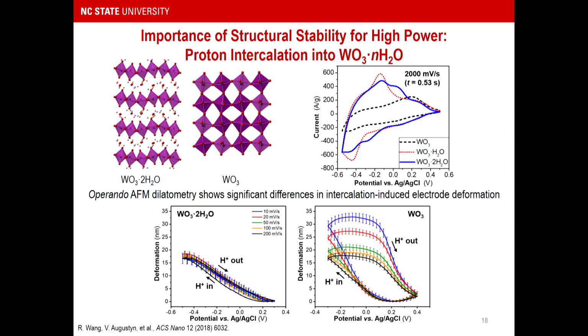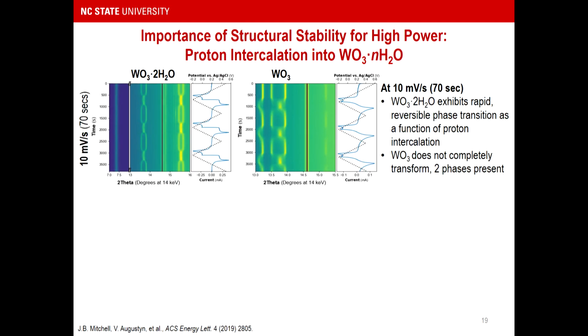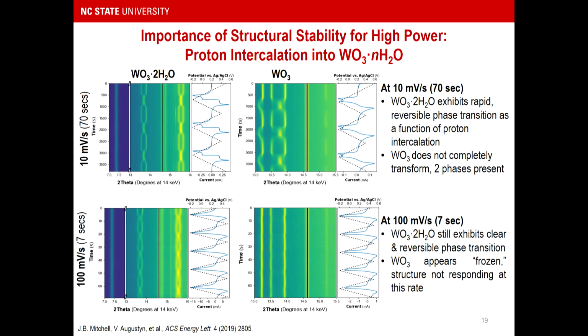but operando experiments told us to maybe consider the structural stability of the water-containing materials, and that's because we saw much smaller deformations as a function of the applied potential when water was in the structure compared to the material where water was absent. Also, we saw no scan rate dependence and very little hysteresis. Again, with operando characterization, we found that the hydrated materials were able to undergo very, very reversible structural transitions at timescales of 70 seconds as well as 7 seconds.